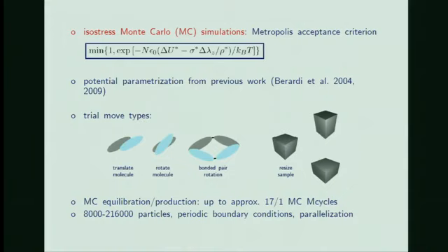So, to find our equilibrium configurations, we do isostress Monte Carlo. We have a modified Metropolis acceptance criterion. What you're seeing here is the probability for the acceptance of an attempted trial move. Instead of having just delta U, the energy difference, we have delta U minus stress times the sample box size along the z-axis, which means that we decided to apply stress along the sample z-axis. We end up with two external control parameters: one is the temperature, like in the normal Metropolis algorithm, and we also have stress imposed from outside. In the language of statistical thermodynamics, this is like performing a Legendre transform.